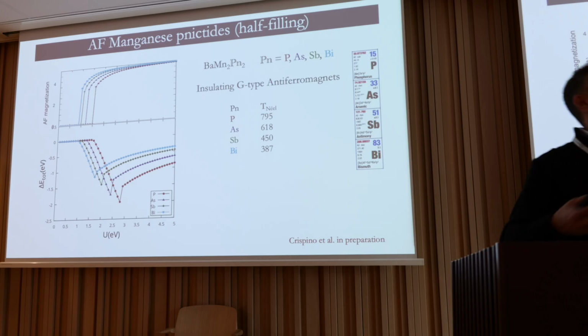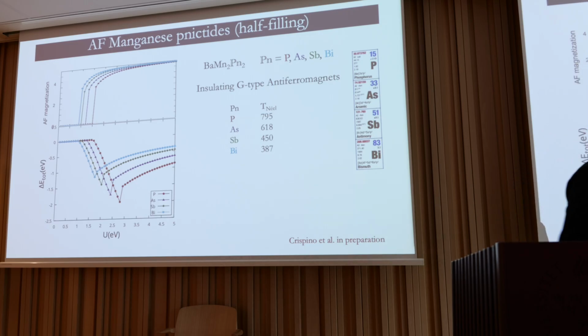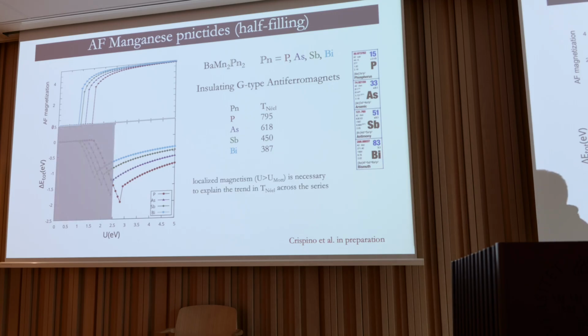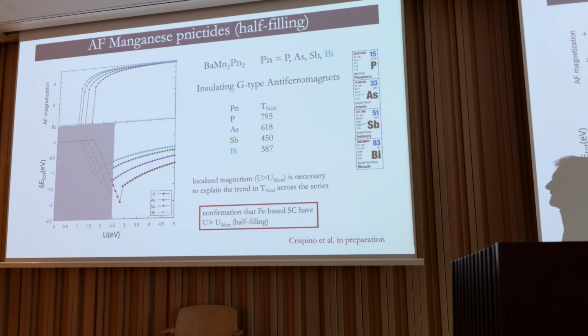We are beyond the U of the Mott transition, and in these compounds, this confirms again that at half filling you have a localized phase. Then it turns antiferromagnetic, but that's not the point. The electrons are localized, they form local moments, and if you dope, you lose the antiferromagnetism, but you have this metallic phase which is dominated by this localized Mott phase that you realize at half filling. For me, this is a nice confirmation of this story: U is larger than U Mott at half filling.